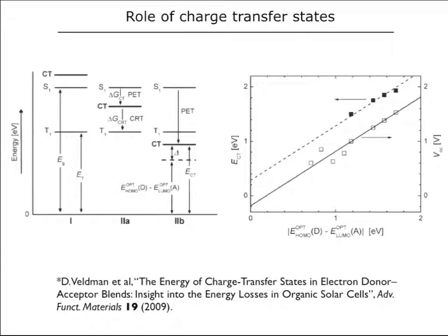So for one thing, if we look at that charge transfer state and we plot on an energy scale relative to the singlet state of the absorber or the triplet state of the acceptor, the only way we're going to get a device to work is if the charge transfer state is lower in energy than both of those. In either of the other two cases, there'll be no charge generation. So we need that CT state to be a little bit lower. Now, the exact details of how much lower and how much loss is associated with that is still a big matter of debate in the field.